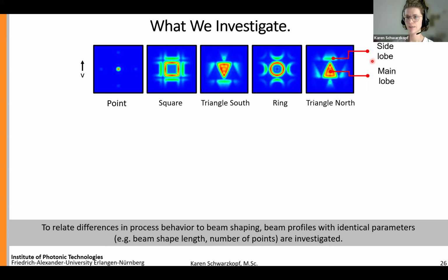And as already mentioned before, the technology of coherent beam combining comes with some restrictions, or at least some things that have to be considered. Namely, not all of the intensity is gathered in the main lobe, which is highlighted here in the red area, but also some parts are located in the side lobes. How this influences our melt pool geometry will be shown in the next two slides. What is important to mention is that the beam shapes here were conceptualized in such a way that the length or width was kept constant in order to really relate differences that are observed to the beam shape itself and not to the size.